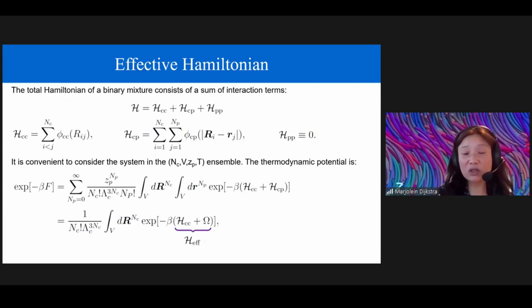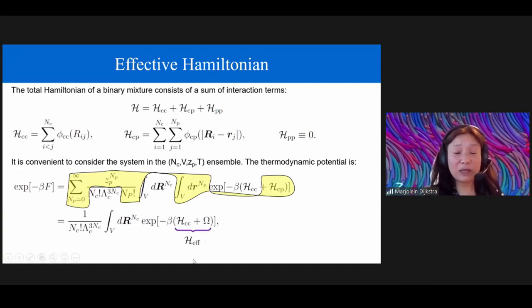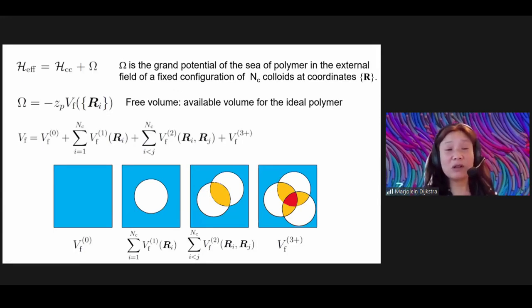And so one can trace out or integrate out the polymers' degrees of freedom in such a way that you arrive at an effective Hamiltonian. And so this effective Hamiltonian is this bare Hamiltonian of the colloids plus this omega, which corresponds to this yellow beast here. And this omega is actually nothing else than the grand potential, the free energy of the ideal polymer in the external field of a fixed configuration of N_C colloids at fixed coordinates.